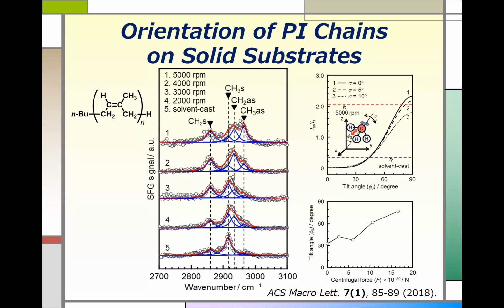Then the structure by spin coating is totally different from that by the solvent casting method. And actually, on the basis of this spectrum, we are able to calculate the tilt angle of this methyl group from the normal direction to the substrate. So you see that with increasing centrifugal force, actually this is proportional to spinning rate, the tilt angle of the methyl group is going to be changed as well. So once we put strong shear, then polymer chains were more aligned at the solid substrate.